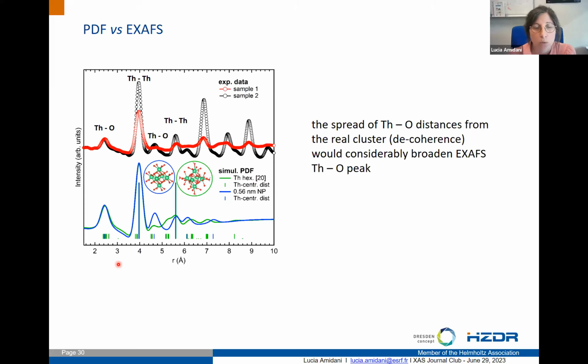And while you see that in my PDF signal, the first peak, despite the presence of different distances, is still not losing intensity. And of course, the most important thing is that this technique has sensitivity not only to the short range, but also to the medium range. So we have higher visibility.